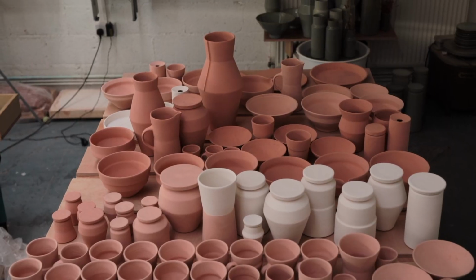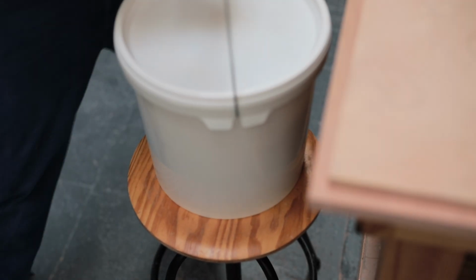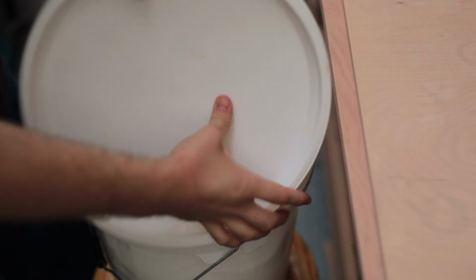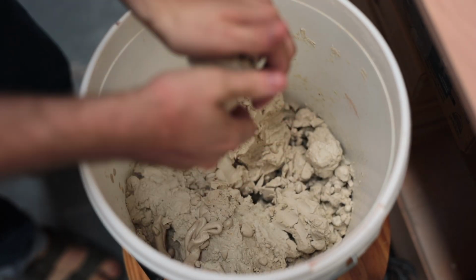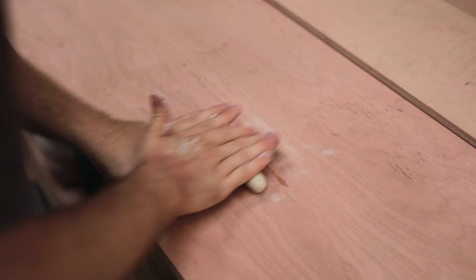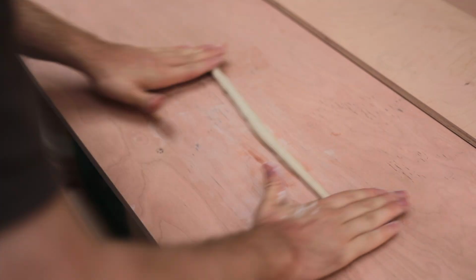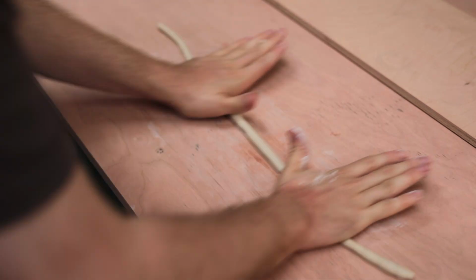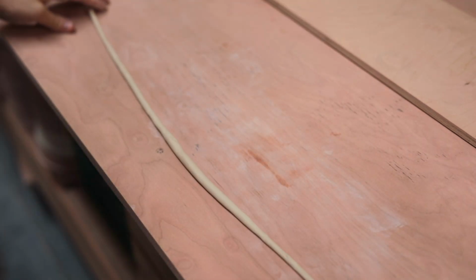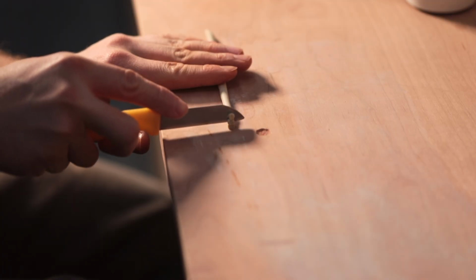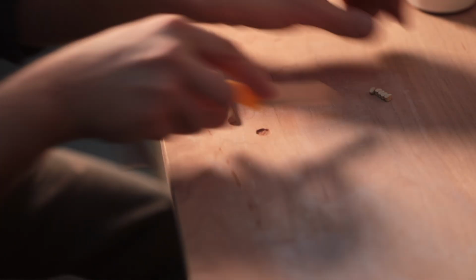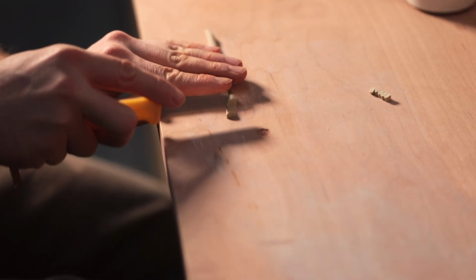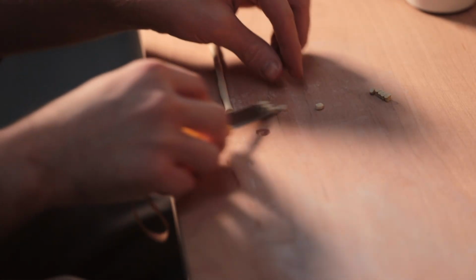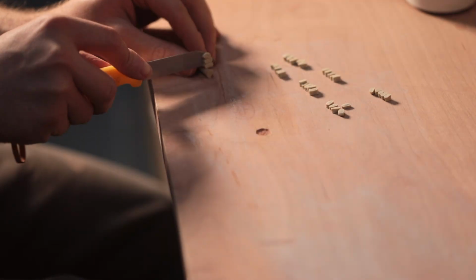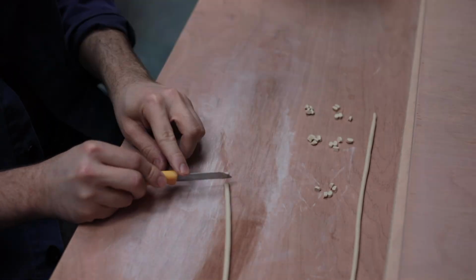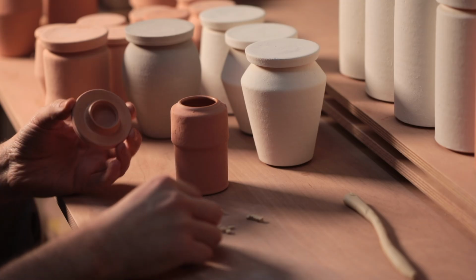And with all the pots now tidied up, there's one step left to go before they can be fired, and that's wadding the lids. This is a clay-like material I mix myself in studio from 50% EPK kaolin and 50% coarse alumina hydrate. This creates a highly refractory material, as the melting point of alumina is some 2000 degrees Celsius. And in this case, I use this material to prop the lids up above the jar in such a way that both parts can be fired together without actually touching. This saves space in the kiln, ensures that both parts stay nice and round, and means that the colours of both components match. As if I were to fire the lid and body separately in totally different parts of the kiln, there's a chance they could differ in colour ever so slightly.